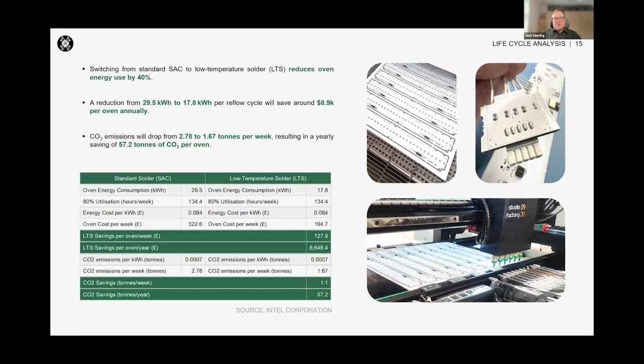We also are able to benefit from downstream benefits of using our material. As we are a thermoplastic, we do encourage users of our technology to use low temperature soldering. So we're actually able to reduce oven energy use by 40% by switching from 265 degrees Celsius reflow to 170. And this allows manufacturers to save nearly 60 tons of CO2 every year per oven.